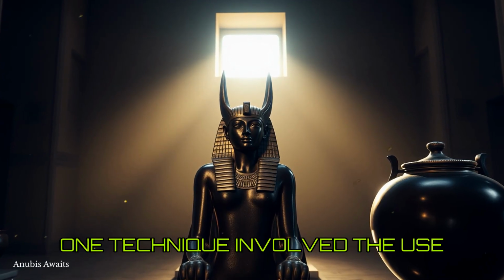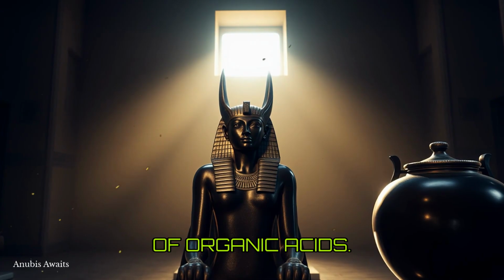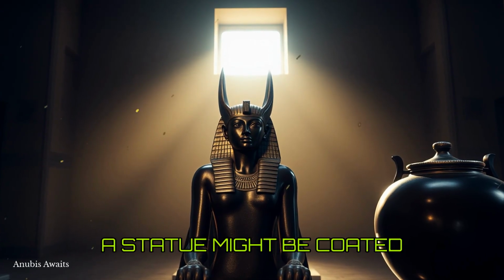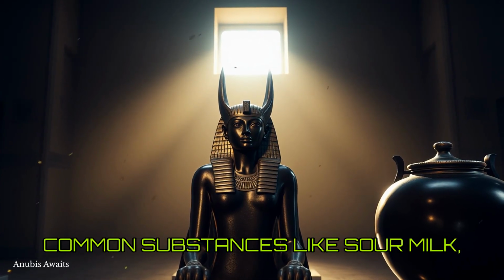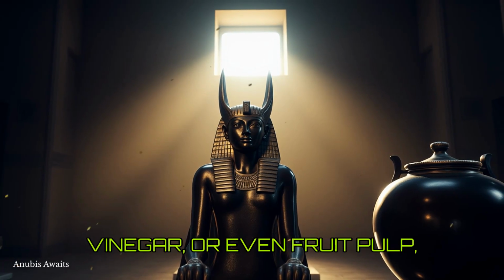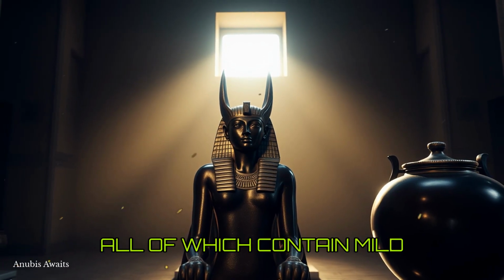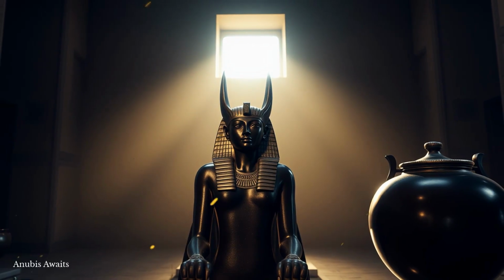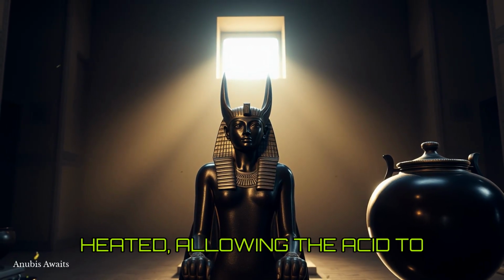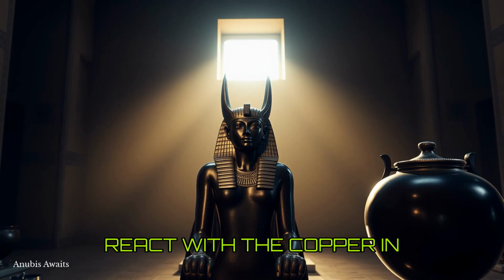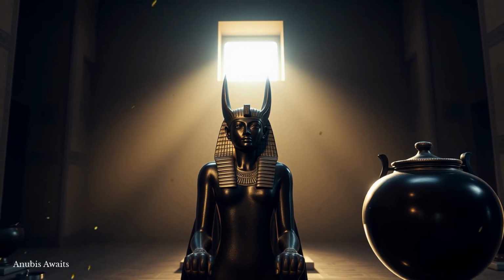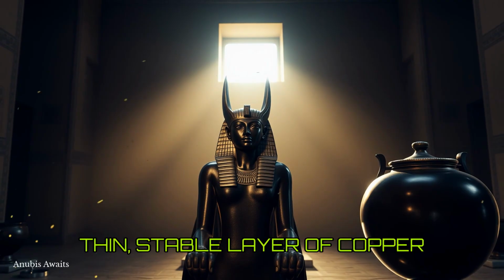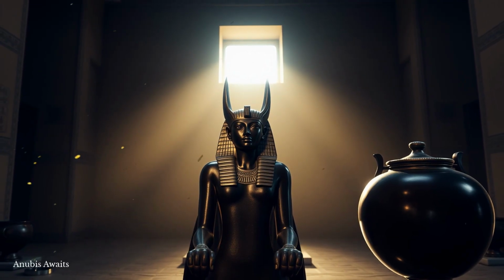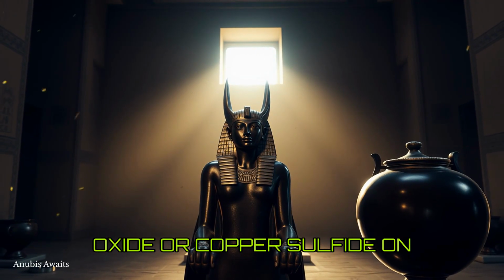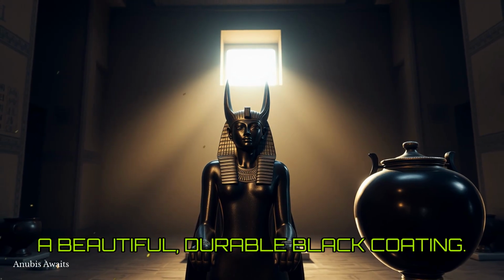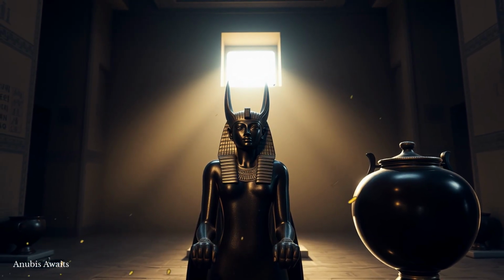One technique involved the use of organic acids. A statue might be coated with a paste made from common substances like sour milk, vinegar, or even fruit pulp, all of which contain mild acids. The object was then gently heated, allowing the acid to react with the copper in the alloy. This chemical reaction created a thin, stable layer of copper oxide or copper sulfide on the surface, which appeared as a beautiful, durable black coating.